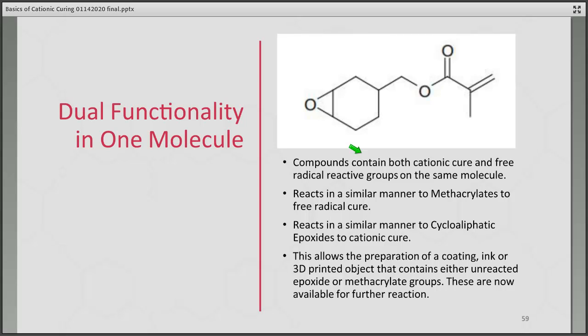And finally, before we leave hybrid systems and our webinar, I'd like to talk about combining both functionalities in one molecule. These are compounds that contain both a cationic reactive group and a free radical reactive group in the same molecule. Here's our cycloaliphatic epoxide joined at the hip to a methacrylate. These are commercially available, by the way, so they do exist and are readily available. These react in a similar manner to methacrylates in free radical cure. They also react in a similar manner to cycloaliphatic epoxides in cationic cure.